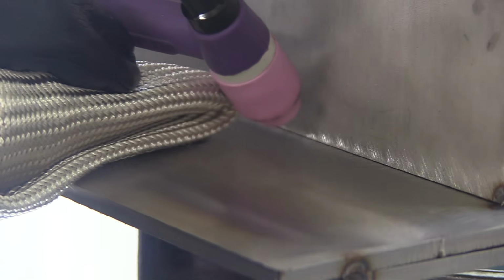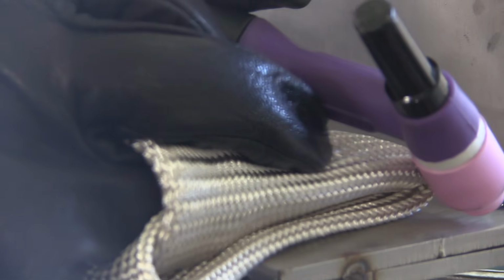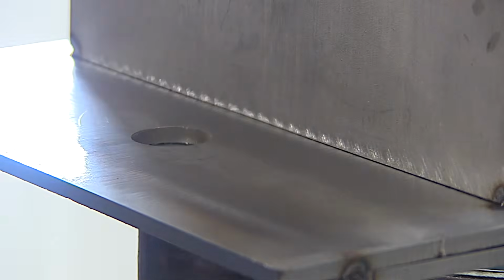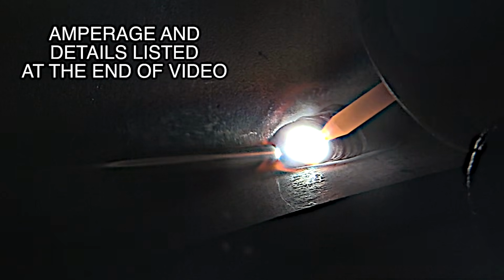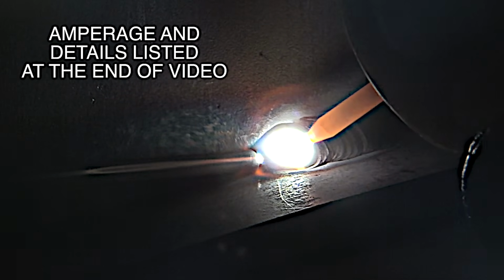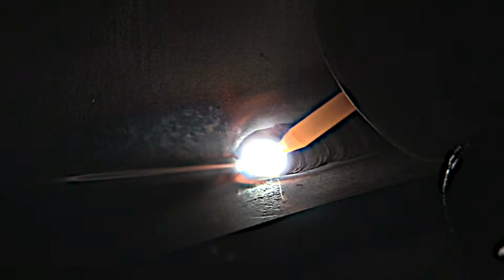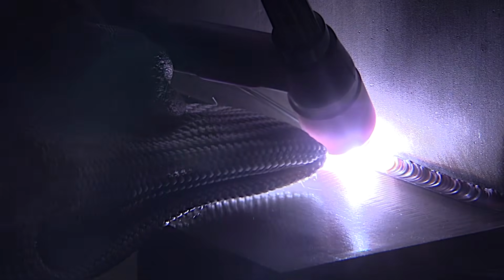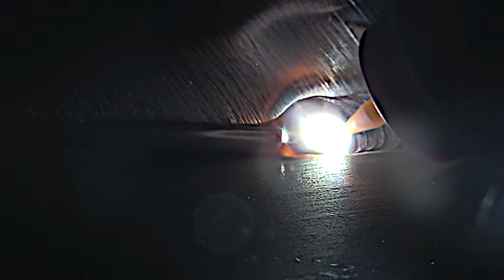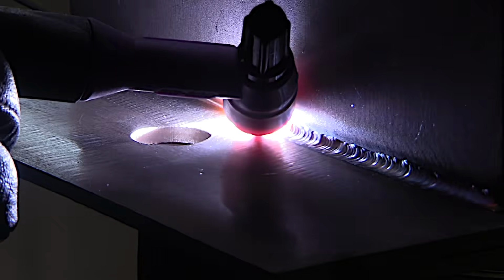Here's a 2-pass fillet weld on 1/4 inch stainless steel. I'm using a number 6 gas lens for this first pass. 150 amps. I'm using what is known as the lay wire technique with 3/32 filler metal, ER308L filler metal. Just leaving that rod in the puddle, but at 150 amps with a good tight arc, it's punching in there.